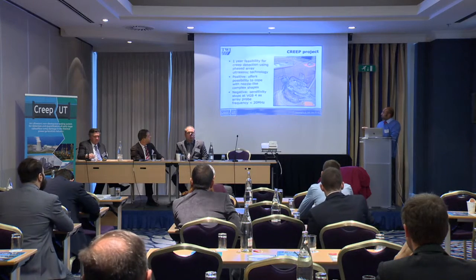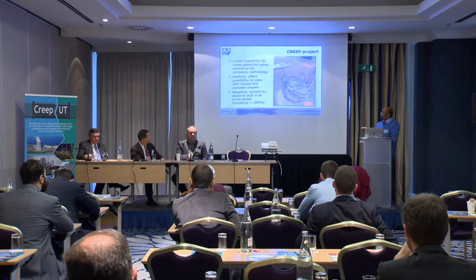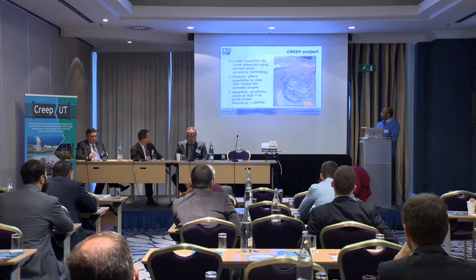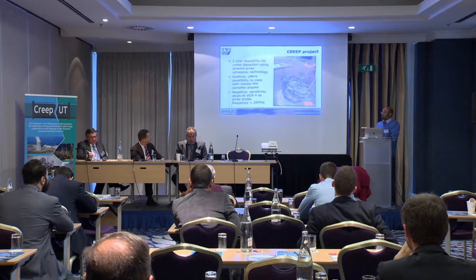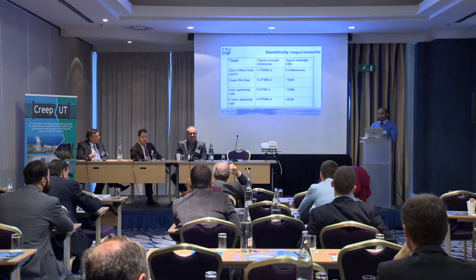But the negative was that we weren't able to prove that we were able to find anything which is earlier stage than level 4, stage 4. And that was primarily, at least at the time, limited by the frequencies that the phased array probes could achieve that were commercially available, which was restricted to less than 20 megahertz. So those were kind of like the findings and key lessons learned.